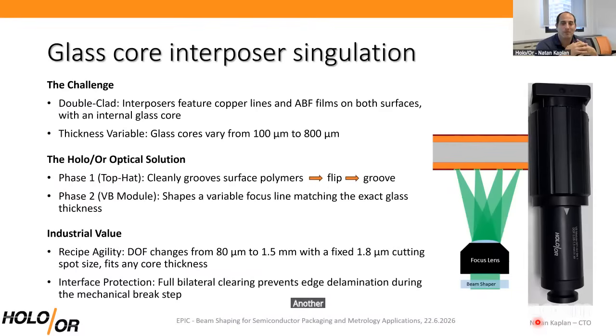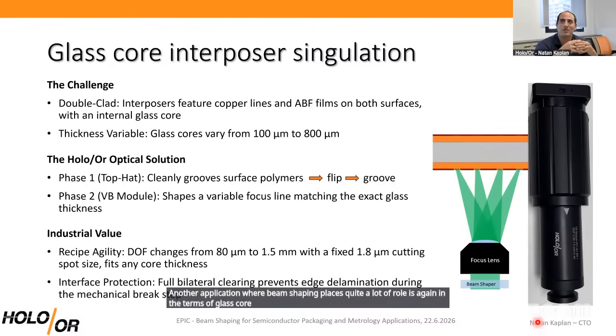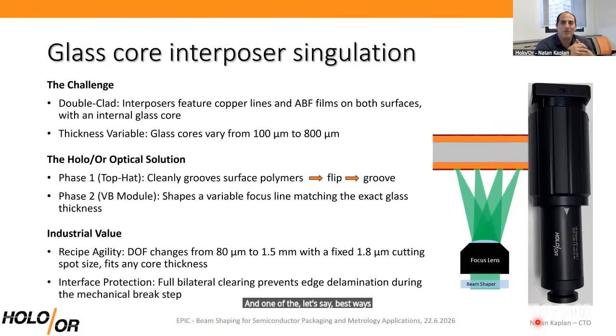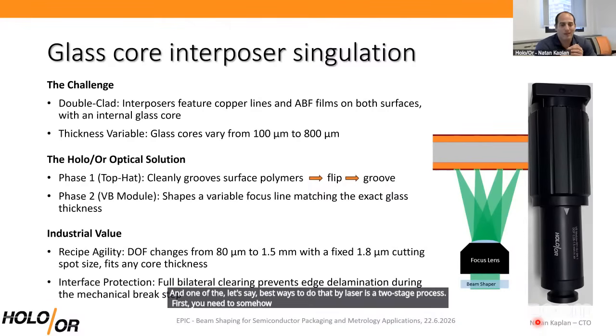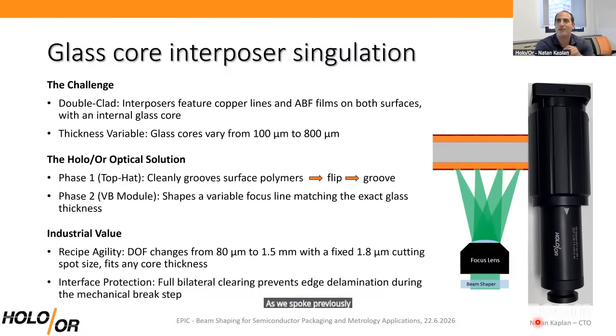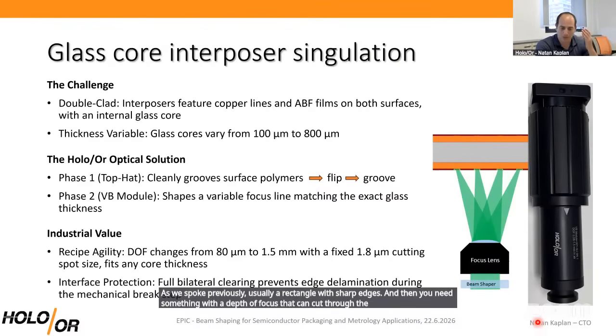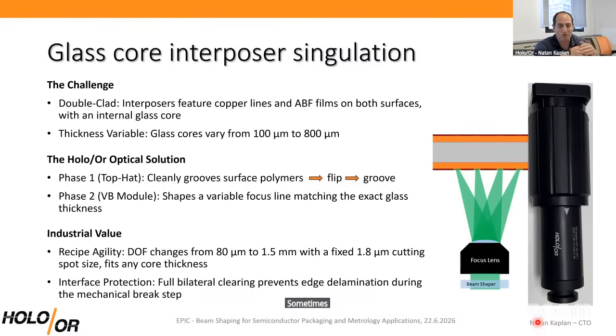Another application where beam shaping plays quite a lot of role is, again, in glass core interposer singulation. Because now you have these glass core interposers, you need to somehow remove from them the copper lines and the ABF films on both surfaces. One of the best ways to do that by laser is a two-stage process. First, you need to groove the sensitive layers so that when you dice the glass itself, they do not delaminate. This is usually done with some sort of beam shaper, as we spoke previously, usually a rectangle with sharp edges. And then you need something with a depth of focus that can cut through the interposer with a good uniformity of lobe. There we have a different solution called the VB module, because these interposers come in various thicknesses from 80 microns up to sometimes even 200 or 300 microns.